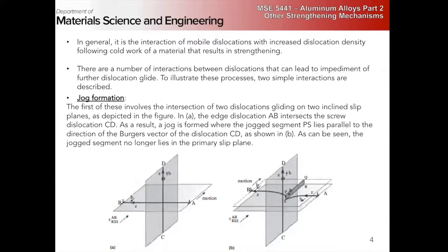Right? They're going to form a jog, right? So it will pass through. You can get it to pass through. But look at what happens to our Burgers vector: it stays the same, right? How do I know our Burgers vector has to stay the same? Because this is a region between slipped and non-slipped region, so we have to maintain a constant Burgers vector.